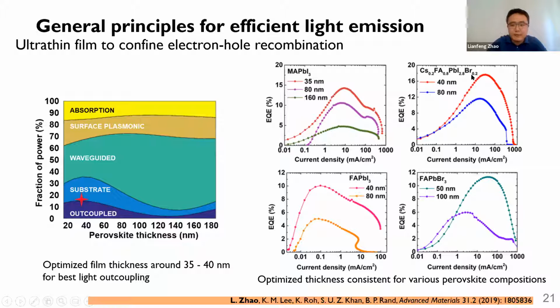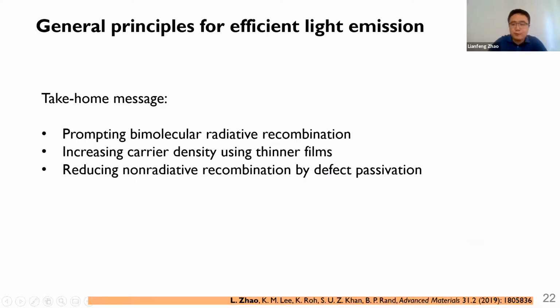Actually, the 17% EQE for this device perovskite composition, I think, is one of the best efficiencies reported for devices without any light outcoupling strategies. So the take home message for this part is that the design principles for perovskite LEDs from the engineering perspective are different compared to perovskite solar cells. And we need to increase the carrier density for better light emission.